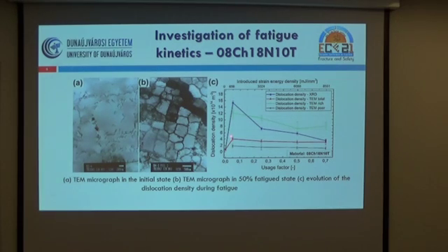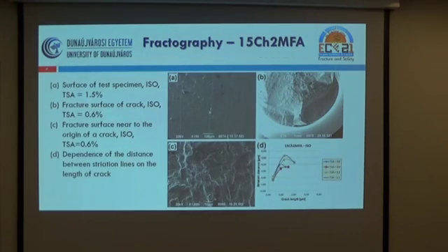So the total shows a quite stable or saturated progress or process. We made scanning electron microscopy on the specimen fractures and fractography on the fatigue crack surfaces. And then you can see here some example.